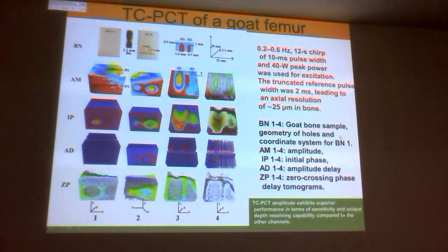So how are the 25 micron and 2 millisecond connected? Shall I infer the velocity of the diffusive wave from these two? Well, there is a diffusivity, that's right. When you look at it, the pulse width was 2 milliseconds. So that means that what you're really doing is repetitive pulses. So you say, how much of a repetition time or delay time do I have to use to see discrete layers? At 25 microns, maybe I added 10 of them or 20 of them for 250 or 500 microns. So these are the depths, 500 microns, 1 millimeter, 200 microns, that's what you're really doing.